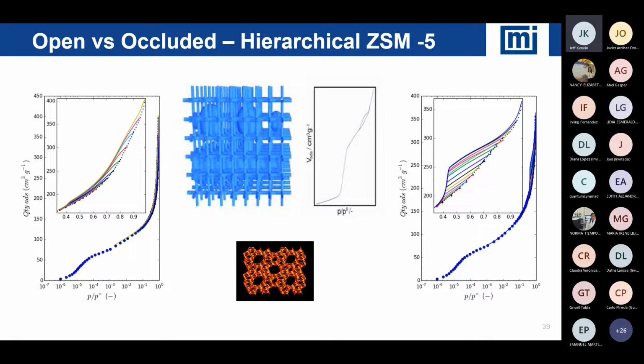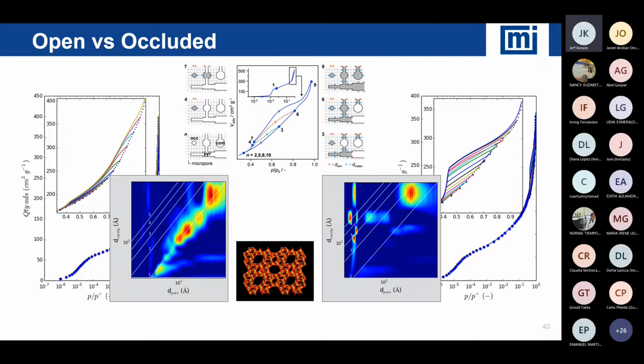If we look at the change in pore size distribution as a function of pressure, we can start to now calculate and understand what is controlling the pore. So on the left side, you see very nicely this pore size distribution. The x-axis is the opening, so the window. The y-axis is the larger pore. So if I have a small window leading to a larger pore, you'll see that relationship. So notice they're all lying on a line of 1. So basically the window and the pore are approximately the same size.